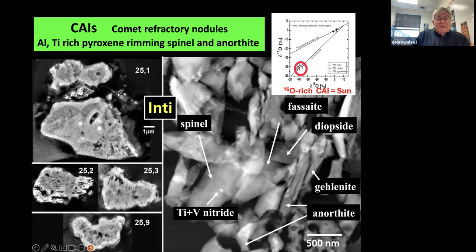Stardust and the Genesis mission were kind of twin missions. One went to the sun, and the other went to the edge of the solar system and collected materials. It was quite astounding to see that we found the same oxygen composition in both places. We found solar isotope compositions, O16 rich in INTI, as Genesis found from the sun by measuring solar wind.